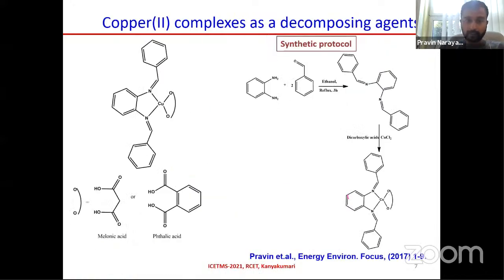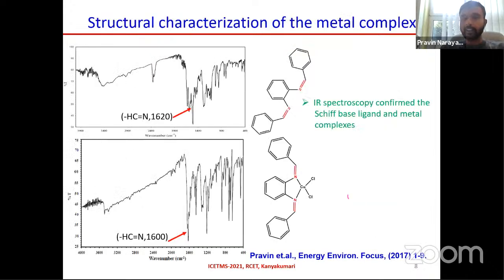So we have designed and synthesized a few copper-2 mixed ligand complexes using Schiff base as a carrier ligand and dicarboxylic acid as a co-ligand. The synthetic protocol for the preparation of the complex is: ortho-phenylenediamine is reacted with two equivalents of benzaldehyde in the presence of ethanol to form the Schiff base ligand, and the Schiff base ligand is further reacted with metal chlorides and dicarboxylic acid to form the corresponding metal complex. And the metal complex is structurally characterized by various spectroscopic techniques.